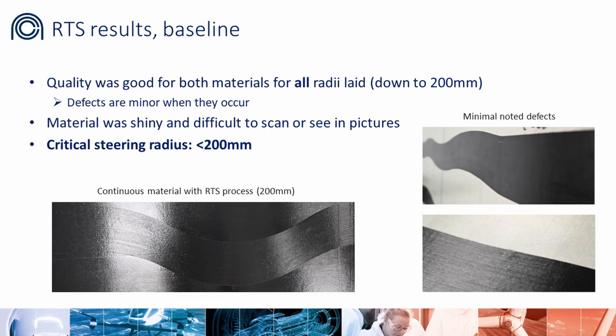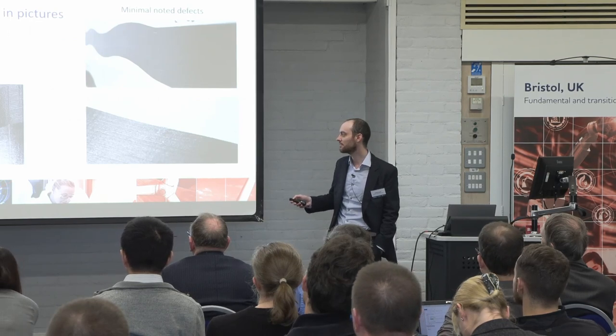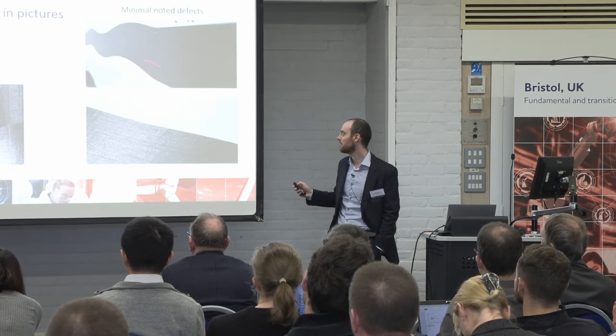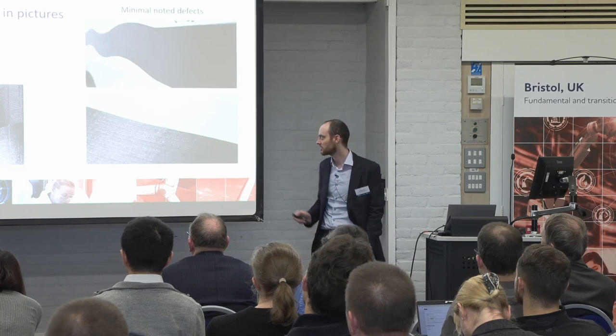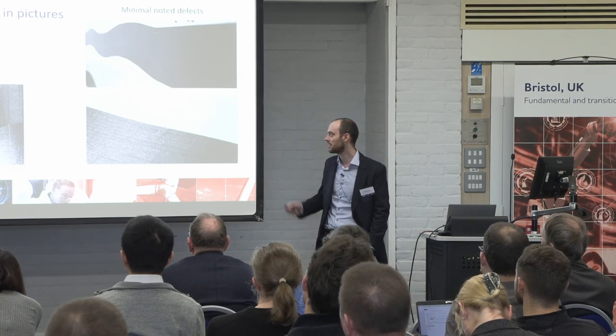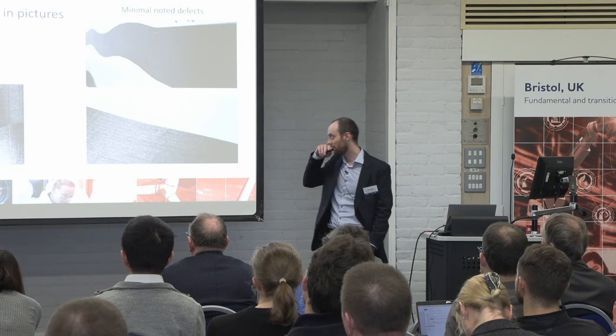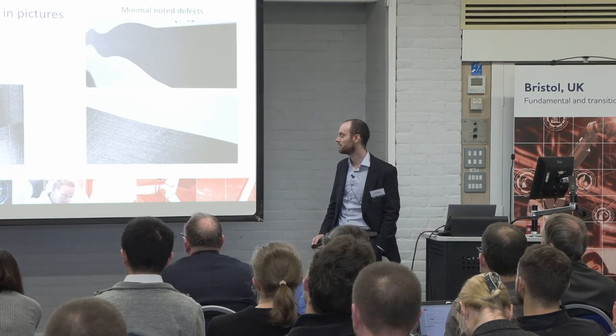And so, long story short, again, I'm not going to dwell too much on this, but we put the baseline material through ICOMAT's rapid tow shearing process, and very much as expected, they were able to produce quite significant steering with very little to no manufacturing defects. You really can't see anything wrong with that, so that's a 5 out of 5 on our defect scale, visually.